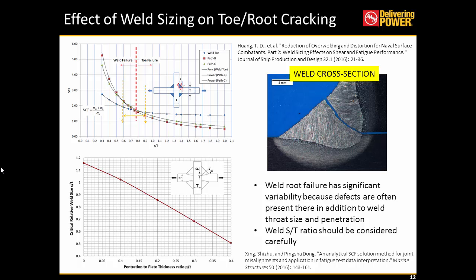So the x-axis represents the total penetration of the weld through the thickness of the material, and the y-axis is the effective S by t ratio, or the weld size ratio. From this plot, what we can observe is that if we are able to get enough penetration, we will still be able to use a smaller weld leg size. This is very important because in this particular case we had a very small effective weld leg size, and as you can see, the penetration is not that high, which led to this throat failure. So it should be a function of the weld penetration and also the weld leg size, which should be carefully considered while looking for the design standards.